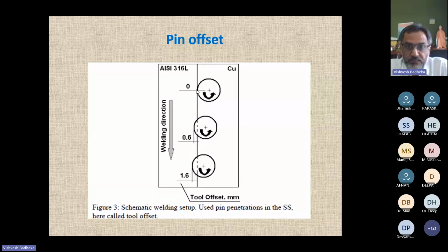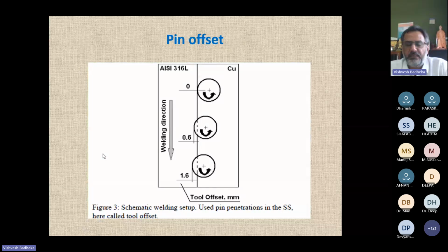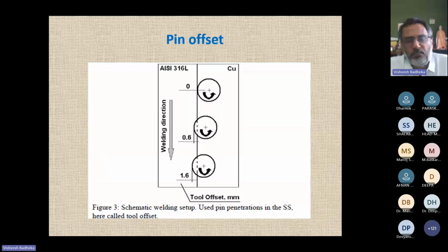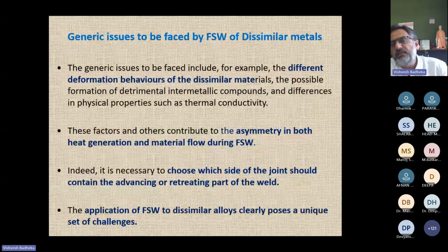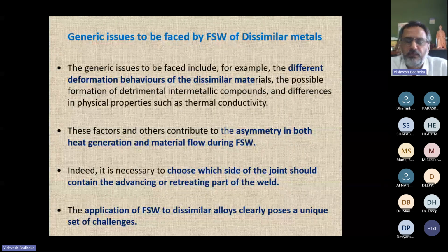So now you can start with the zero offset, you can go with 0.6, you can go with 1.6, right? Slowly and gradually you are increasing the contact with the hardened material, and then you can optimize the offset for a given material combination for a given pin dimension. And these different offset values give you different mechanical properties, right? So that's very, very important that you need to optimize.